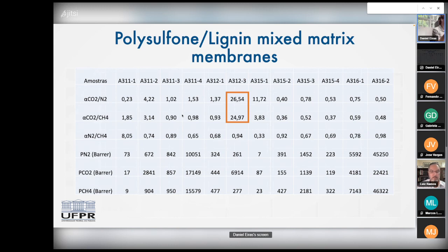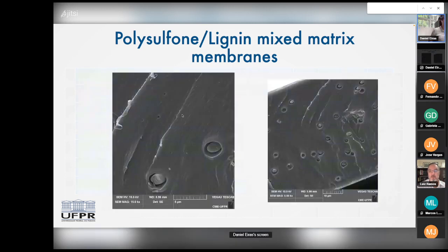So some of the samples have better selectivity. Some have a worse selectivity or no selectivity. To try to understand what's going on, we did many tests and we ended up with the SEM results of our nanocomposites. As you can see here, we have a particle that is inside the polymer, and there's a huge defect